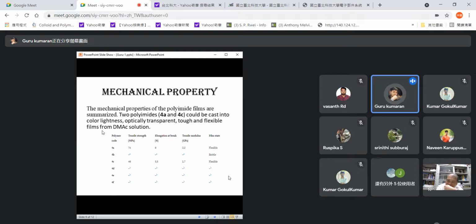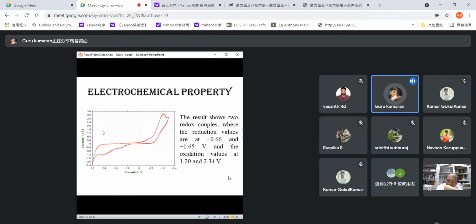Comparatively, 4a and 4c should be more flexible than the others. And this is the electrochemical property of the polymer. This diagram shows the reduction values at minus 0.66 and minus 1.65 volt, and the oxidation peaks at 1.20 and 2.34 volt. This shows it is a good acid sensor.